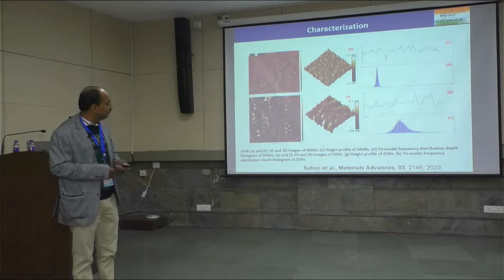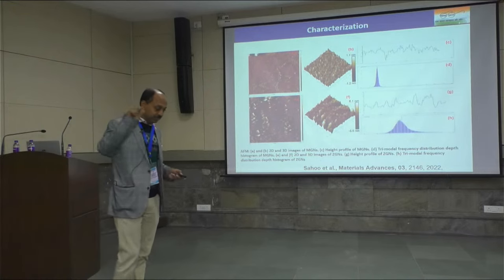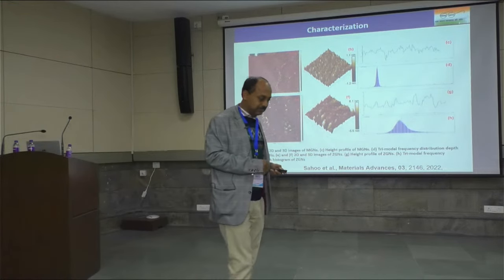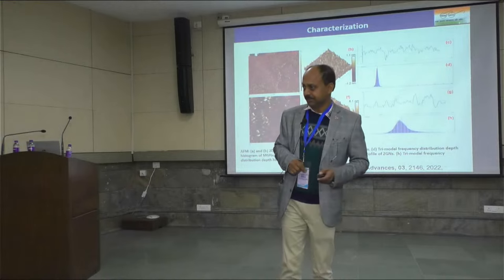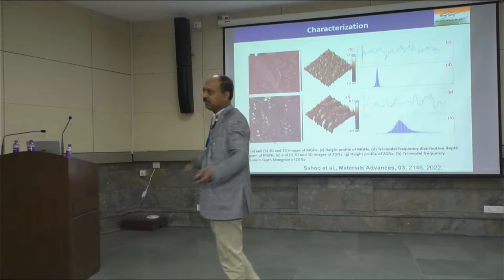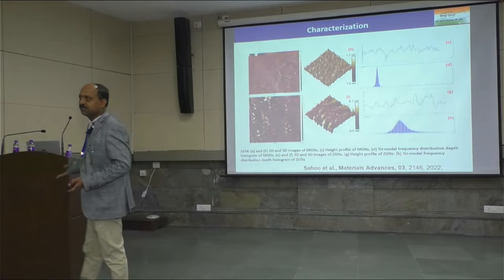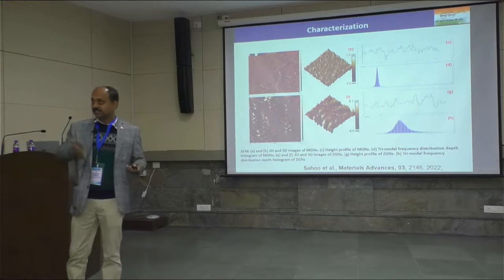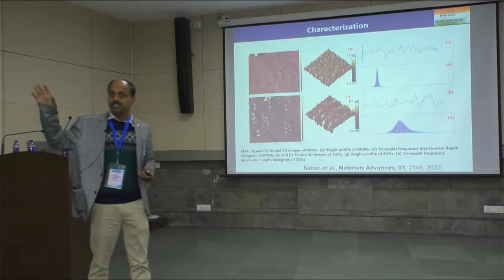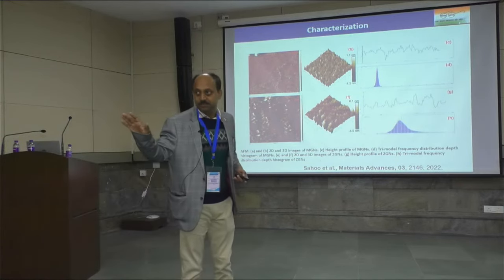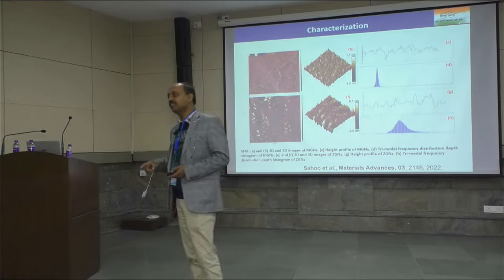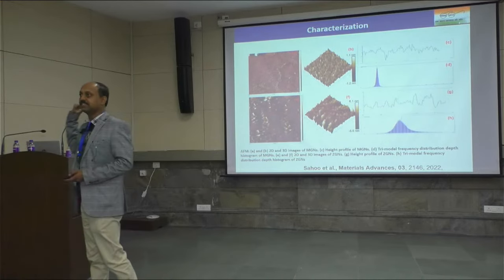This is the AFM. From AFM, the thickness of the layer is near about 0.8 nanometers, and 0.8 nanometers means that it has near about 2 layers of graphene. I think the DFT studies also say that there are 1 to 2 layers of graphene. But I don't believe this is one layer of graphene, because it is very difficult to develop one layer of graphene in this method.